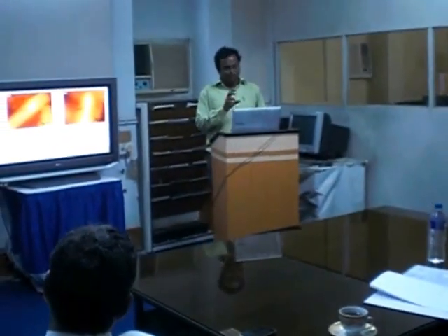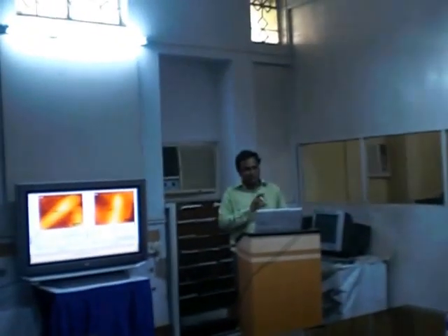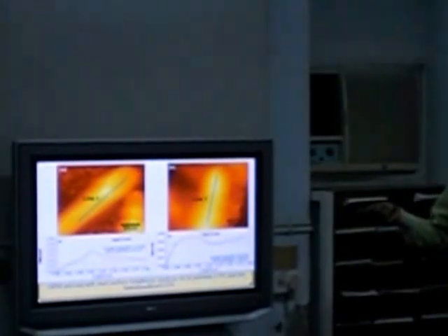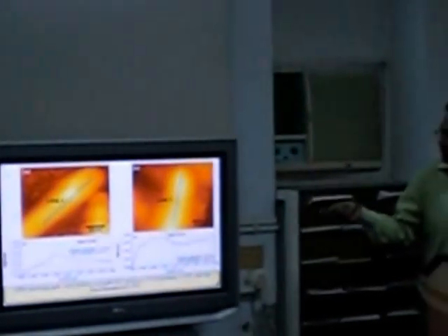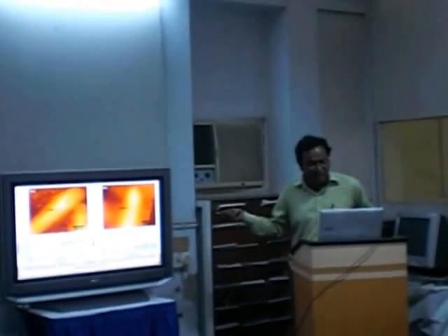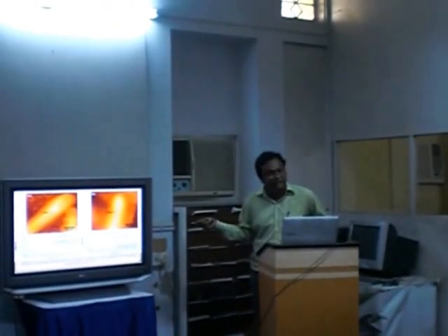The carbon nanotube is chemically functionalized, with oxidation groups populating the carbon nanotube. We have taken the surface roughness of the carbon nanotube. This one is a single carbon nanotube which is non-functionalized, and we checked the roughness profile, and this one is the functionalized carbon nanotube. Definitely there is possibly a lot of noise because we can't do a very fine experiment, but we have shown the surface roughness is increased in the functionalized carbon nanotube.